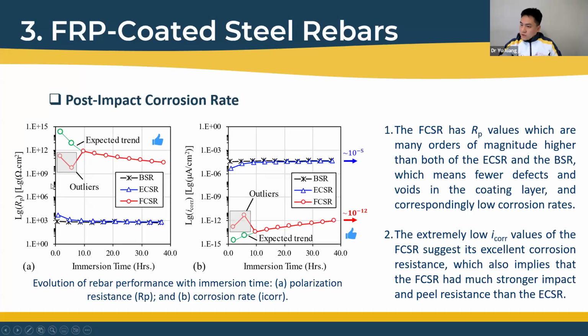This is the corrosion polarization resistance, and figure B shows the corrosion rate. From this figure, we can find the black line is the bare steel rebar, which is the control. Because the steel got direct contact with the saline solution, the corrosion rate was very high for bare steel rebars and remained almost consistent.